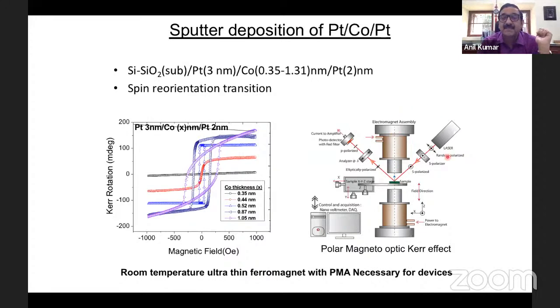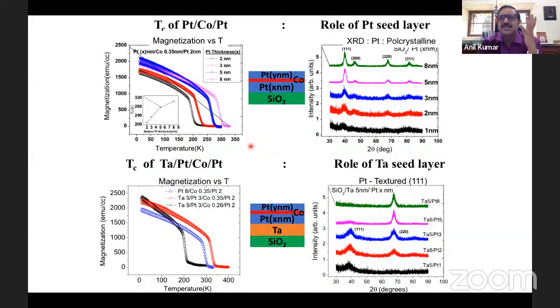So this is the setup for this magneto-optical Kerr effect. You have polarized light falling on here. You analyze the polarization of the reflected light, and then you plot the rotation, that means the change in the polarization axis, as a function of applied magnetic field, and you get all this hysteresis loop. And also, it's very important to grow very high quality metallic layers to get this phenomenon.